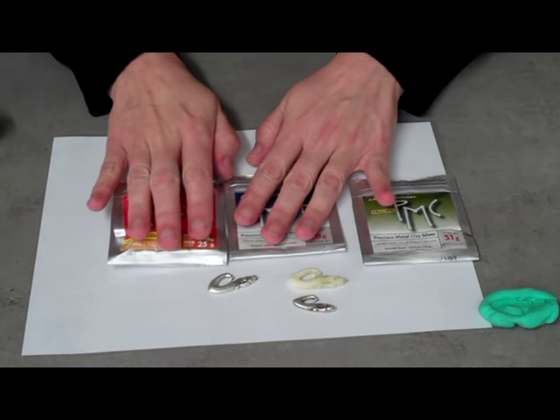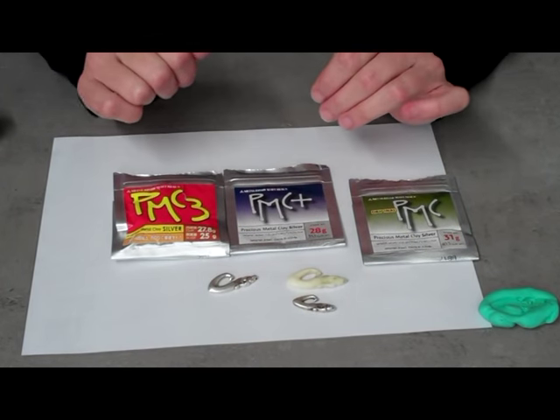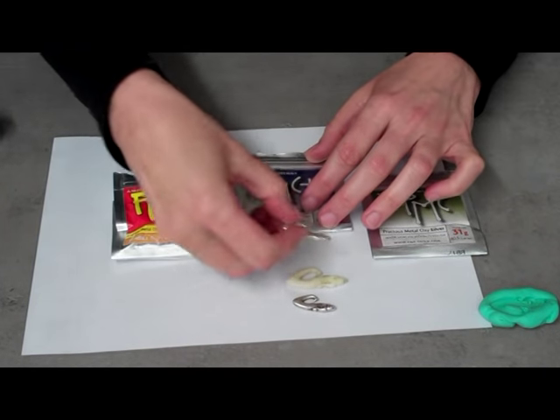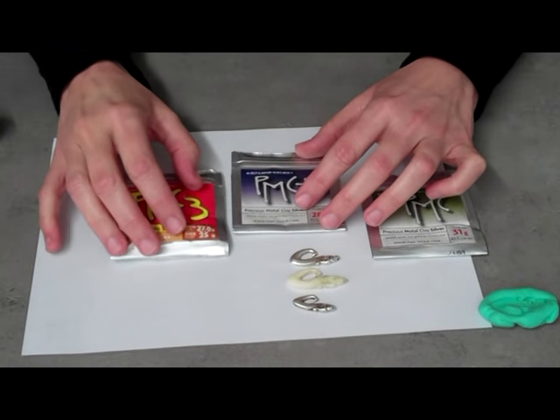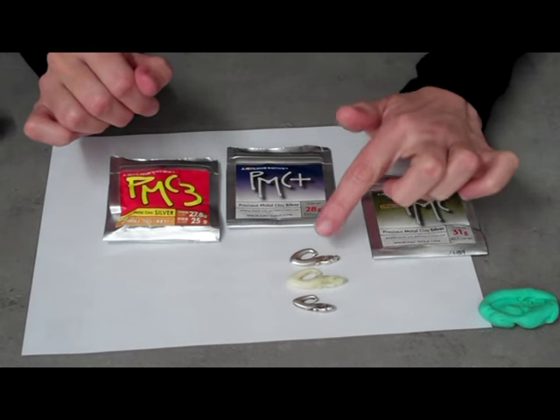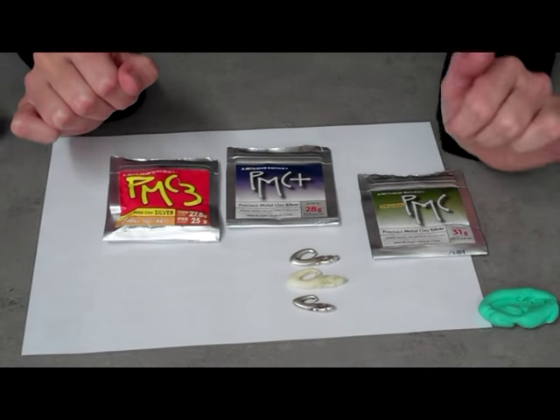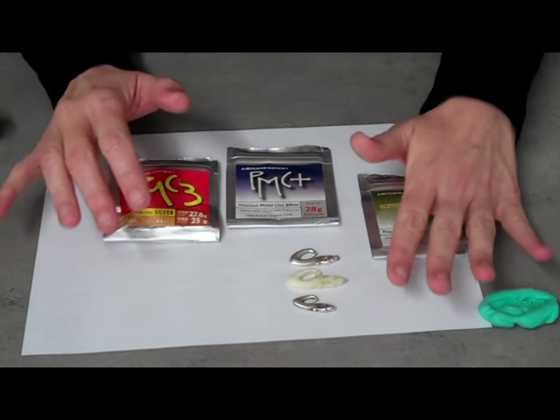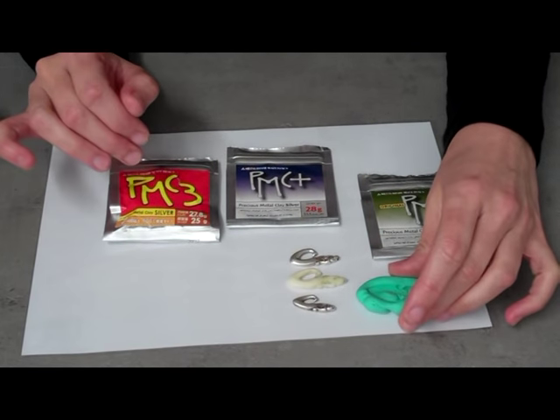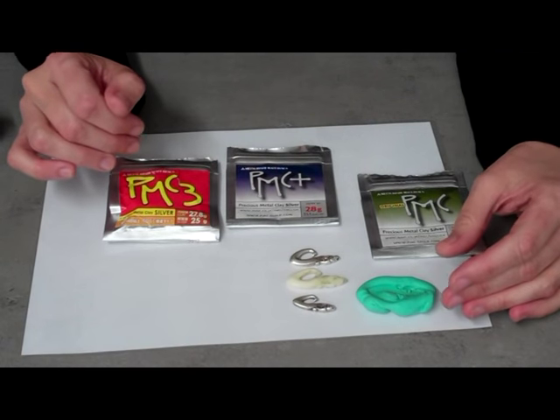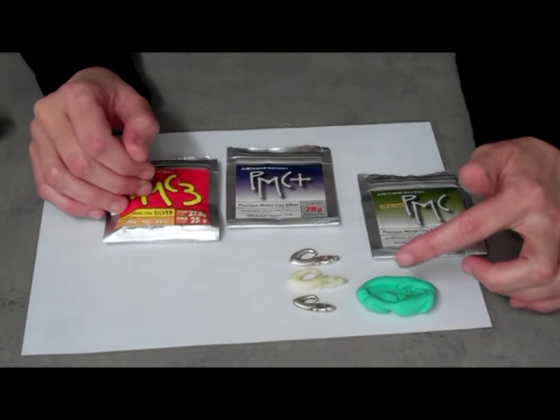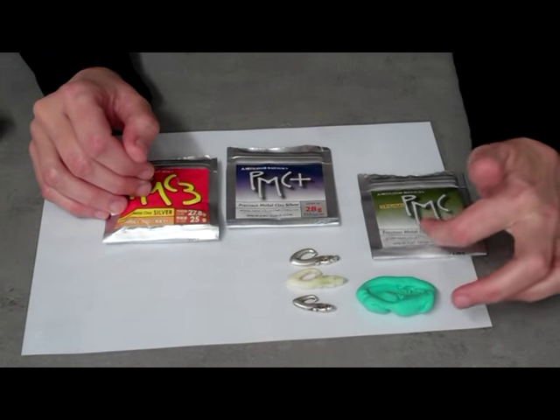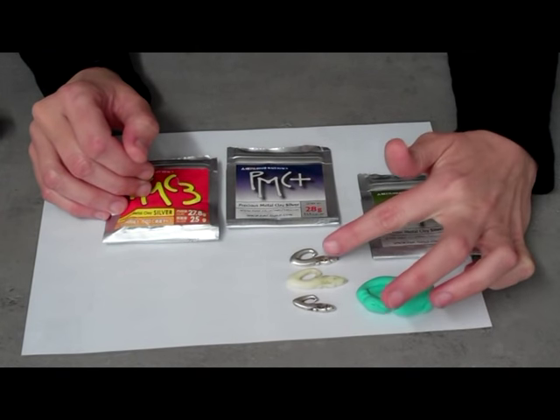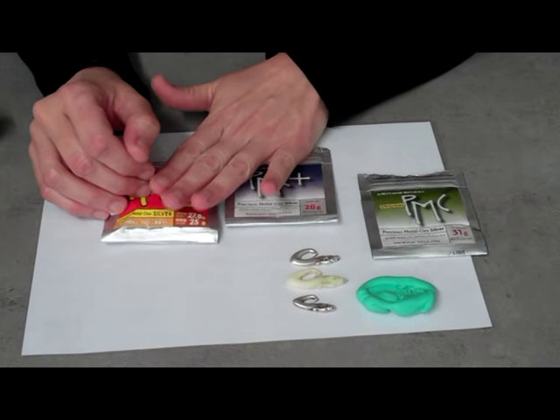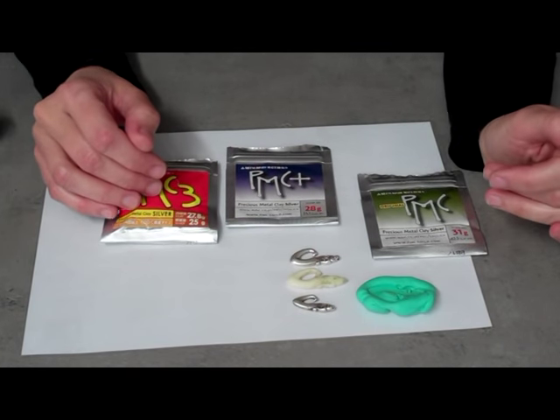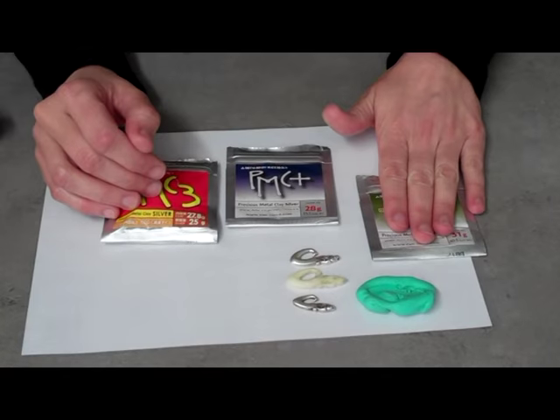And then both of these two shrink by between 12 and 15%, and that's what that looks like. They're both kind of about the same shrinkage, so you can see it's not quite as dramatic as the PMC original. And there might be times when you want this shrinkage. If you only had one mould, and you wanted to make a set, a pendant and earring set, say for instance, you could use the shrinkage properties of this higher shrinkage clay to give you the smaller earrings, and use either one of these clays to give you the less shrinkage. But you do have to have a kiln for this.